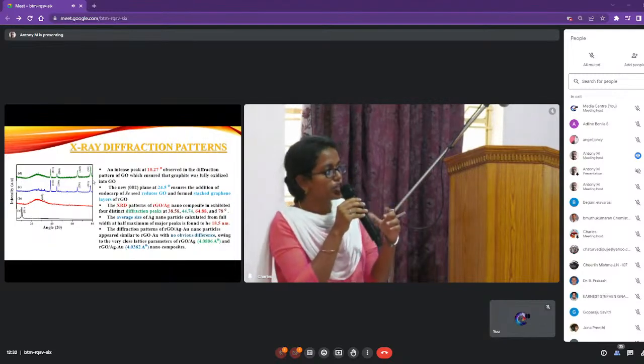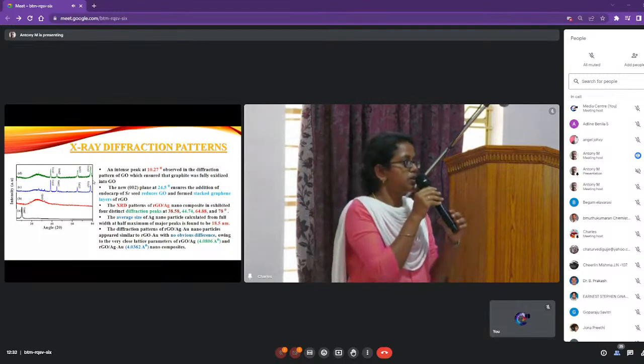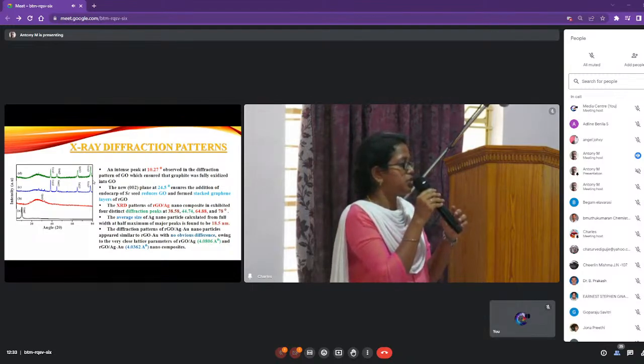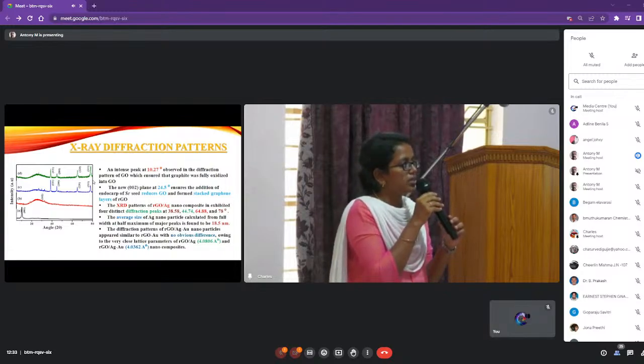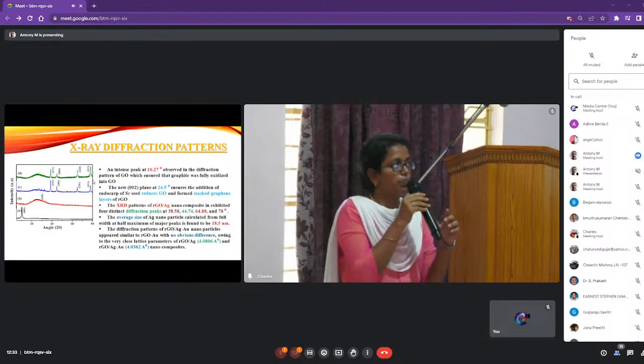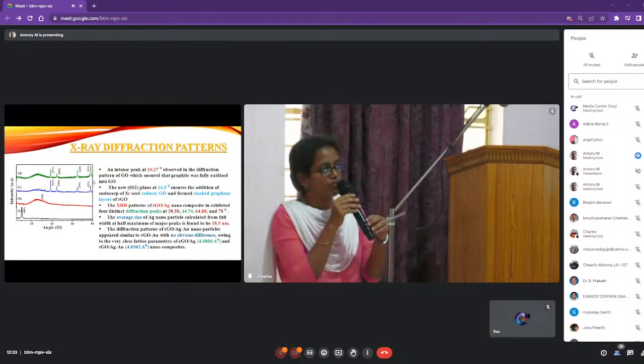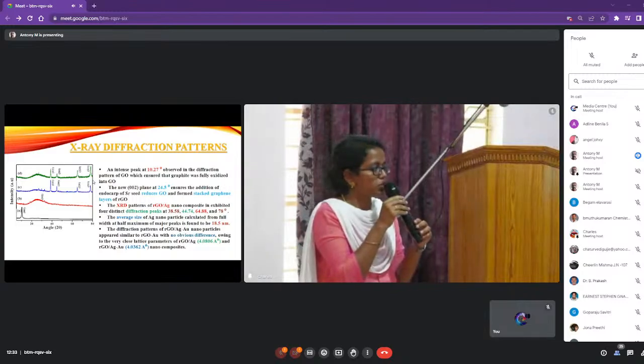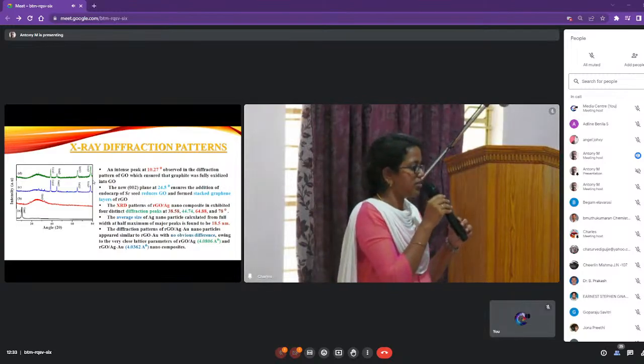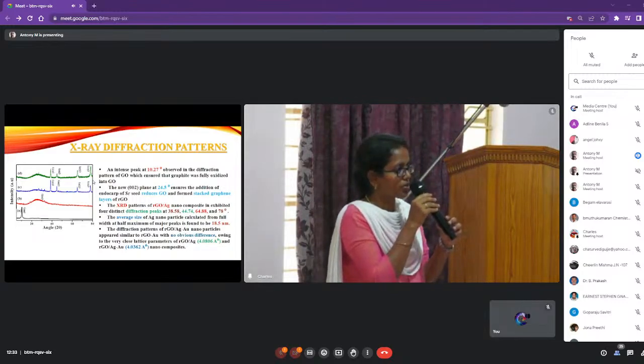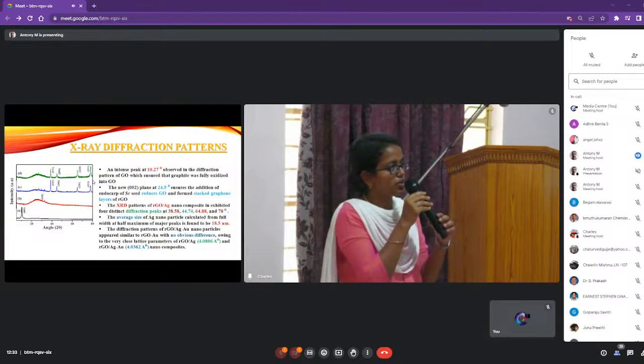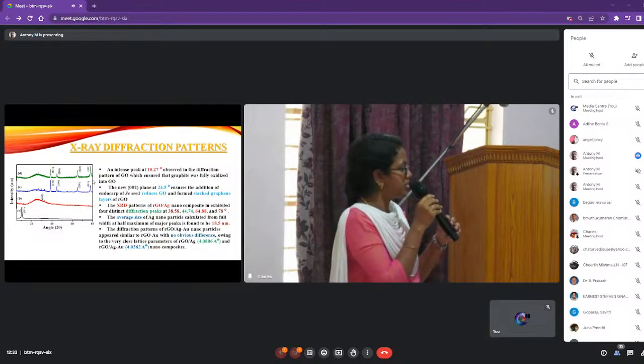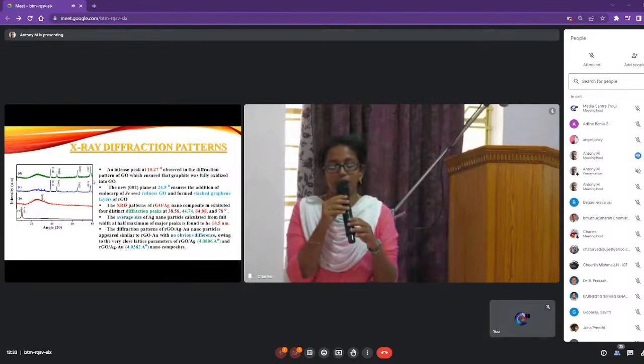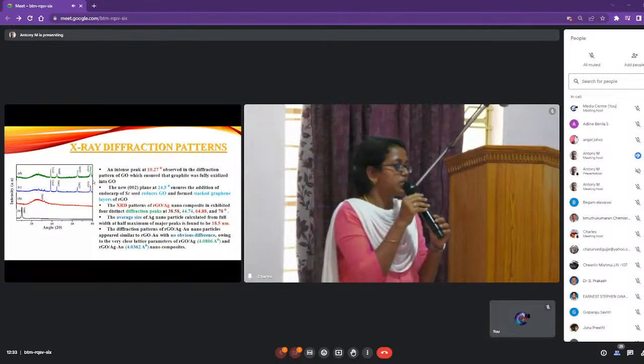And the XRD pattern shows the first, A, shows the peak of the graphene oxide, which confirms the presence of graphene oxide at 10.27 degrees, and the second, B, shows the presence of reduced graphene oxide, which has a peak at 24.5. The third and fourth show the presence of reduced graphene oxide Ag and reduced graphene oxide Ag and Au nanocomposites. The 3 and 4 are more or less similar, which shows no obvious difference. That is because of their very close lattice parameters.